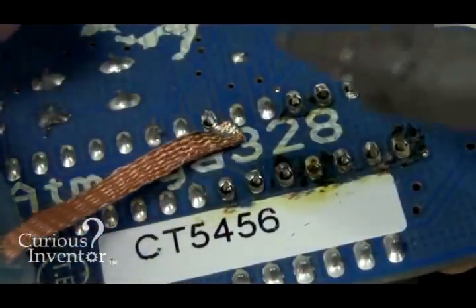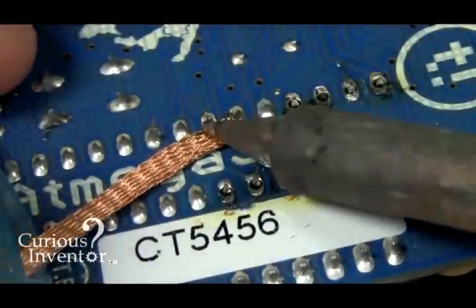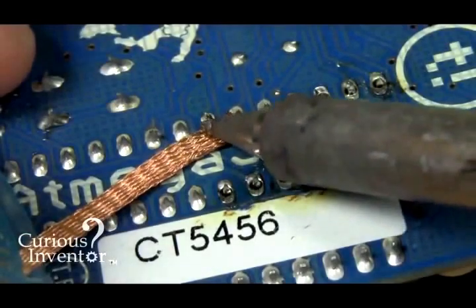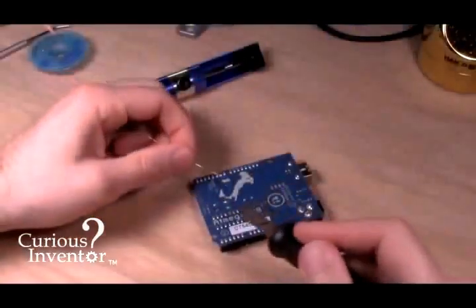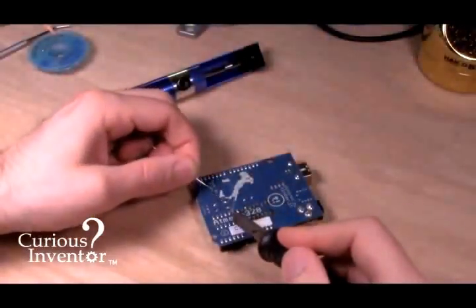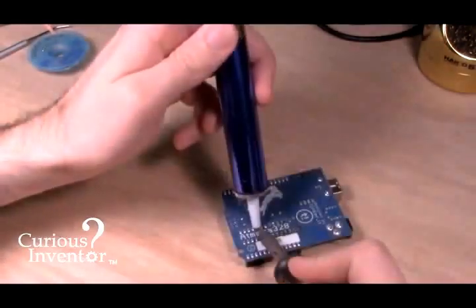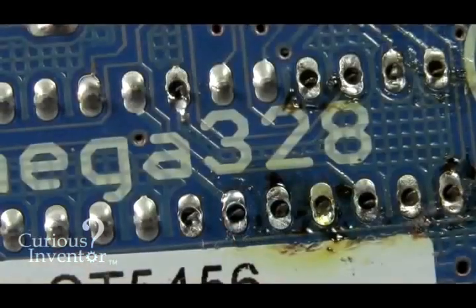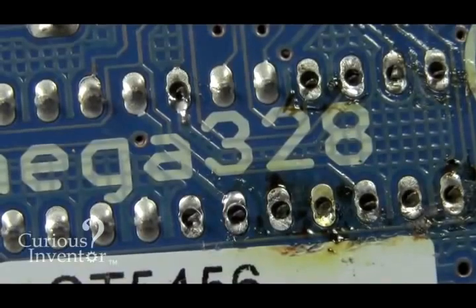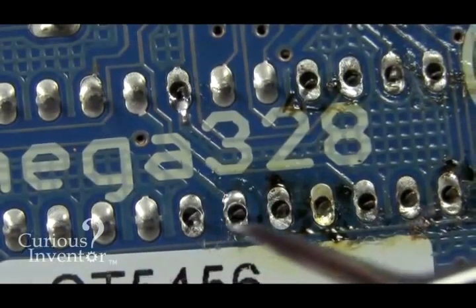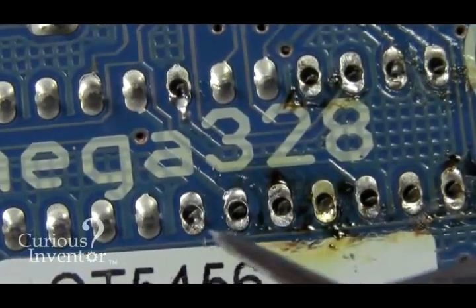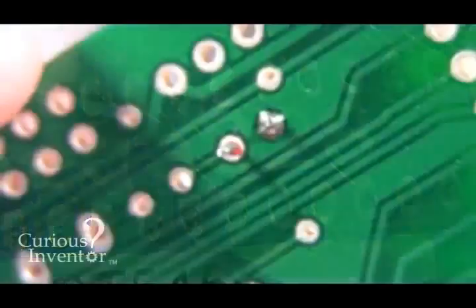If there's too much solder remaining to easily break the pin free, you might have to use wick to clean up what's left. If you don't have any wick, it's sometimes easier to resolder the hole and try again rather than continue to use the solder sucker on a mostly empty hole. If the joint is mostly empty, it will be difficult to get the remaining solder completely molten with the iron, and also difficult for the solder sucker to create much of a vacuum.